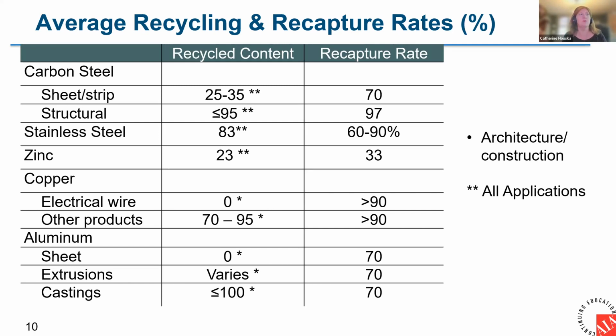For copper, electrical wire has to be pure virgin material. But other products can have 70 to 95% recycled content. Aluminum sheet, at least the aluminum sheet that is used on buildings, generally doesn't have recycled content. Sometimes there is data published that averages the beverage cans in with other types of sheets, and it's important to make sure you're looking at the right information. Extrusions and castings can have a lot of recycled content, so that sheet that might have no recycled content can be used elsewhere. But I thought this might be helpful to understand the metals that you're using.